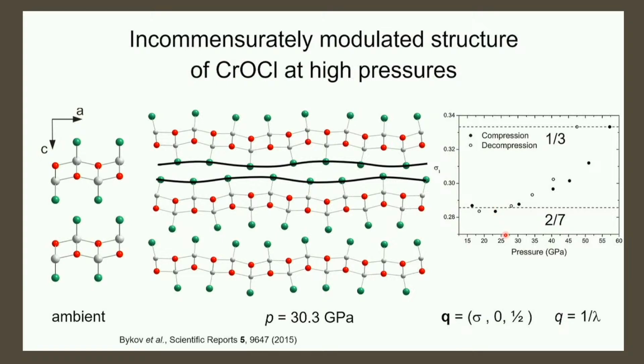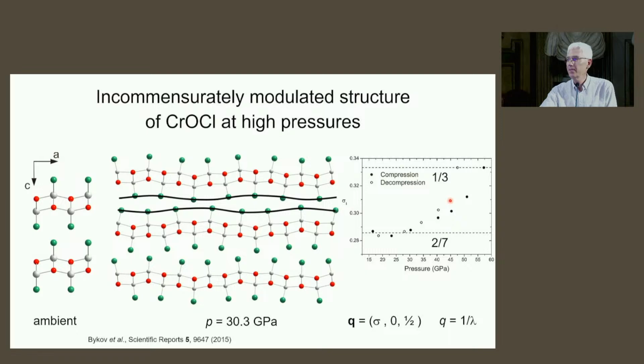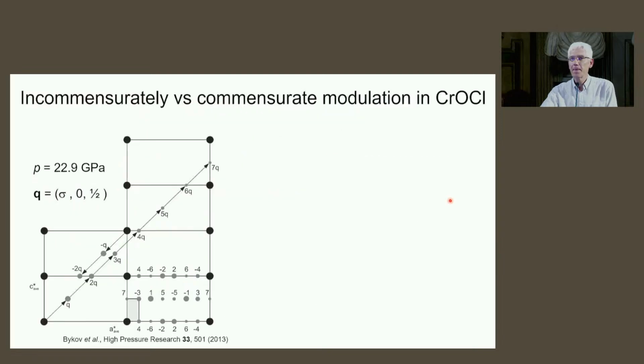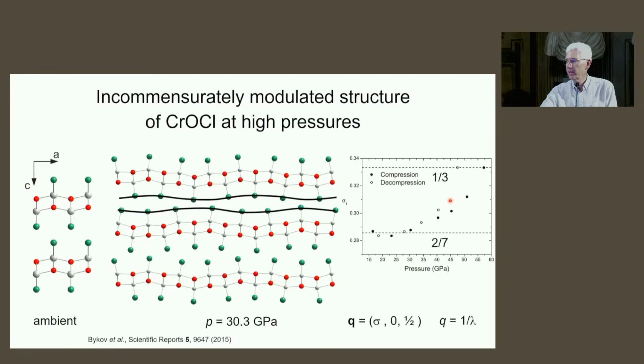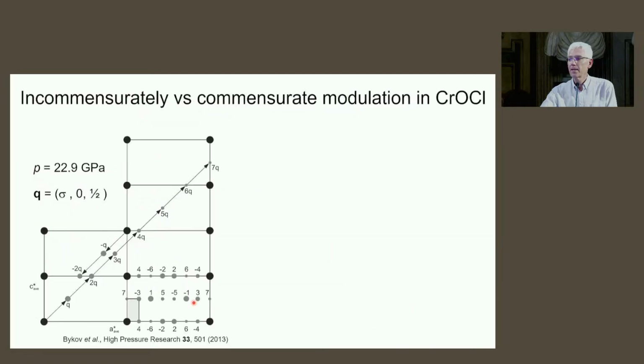Maybe this is an experimental error, the deviation. Maybe it is incommensurate. Maybe. And that's very difficult to determine. One reason it's very difficult is that with sigma being 2/7, and maybe I should point out, 2/7, 0, 1/2, I need 14 steps to be back at 3 integer numbers. That means if it is 2/7, it's commensurate, but we have 14 of these satellites and also 14 unit cells to make a supercell, to make it periodic again.